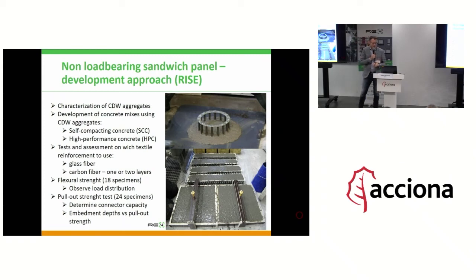And when it comes to these self-compacting and high-performance concrete, then you obviously start with some kind of mix design you already have, but you try to optimize by replacing as much aggregate as possible with CDW, but still keeping the requirements of the industry. So for example, Creag had requirements on us for a certain slump flow, workability, and also, of course, strength development and final strength.